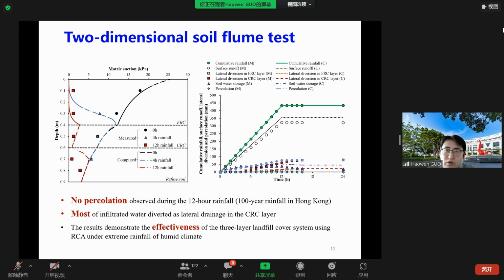So with the rainfall continued, lower soil suction returned in the shallow depths. This reduction of the suction means the breakthrough of the capillary barrier formed by the top two layers of the soil concrete. At this point, the function of the middle layer can transfer from the barrier break to a drainage layer, so that it still can function to reduce the further infiltration into the bottom layer.